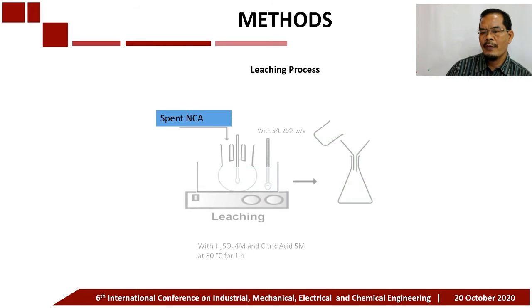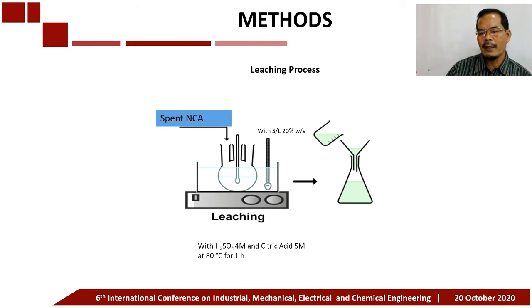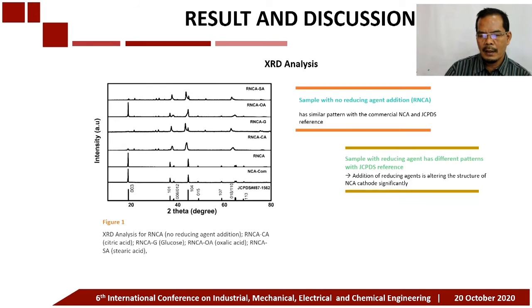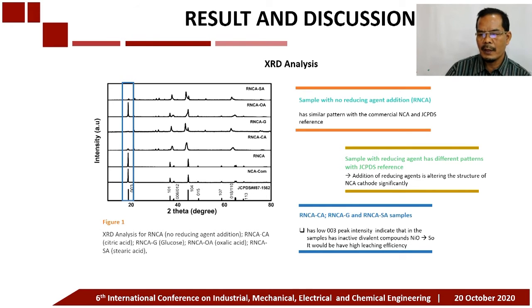The second step was the leaching process. The spent NCA obtained from the pretreatment process was mixed with leaching solution of a certain concentration. The condition of leaching was 80 Celsius degrees with a duration of 1 hour. The ratio of solid to liquid was 20% weight per volume. As I said before, the solid obtained from pretreatment was examined using XRD.